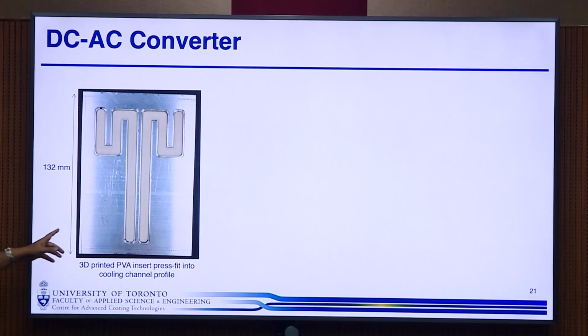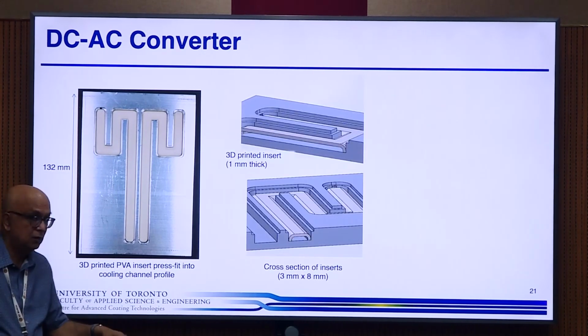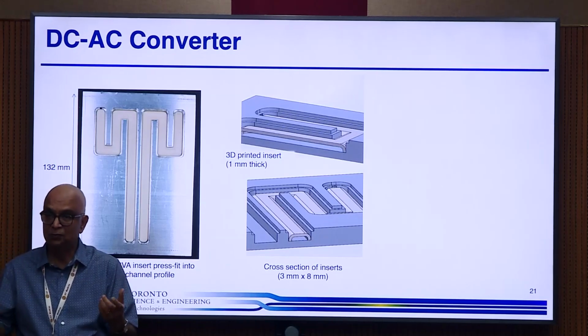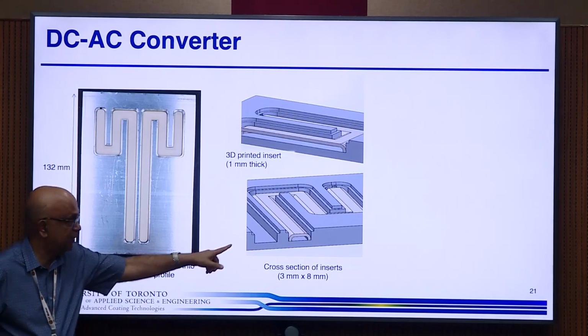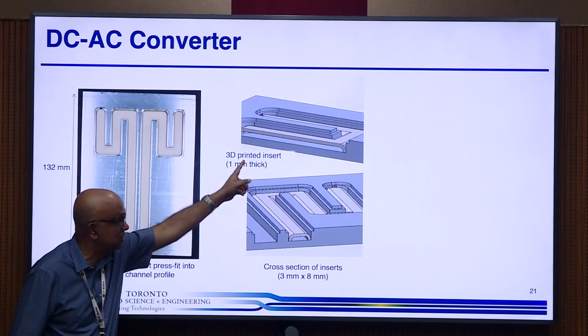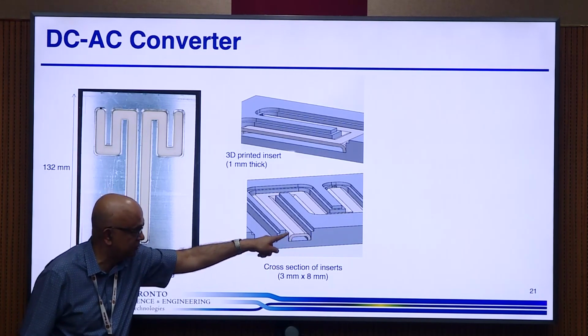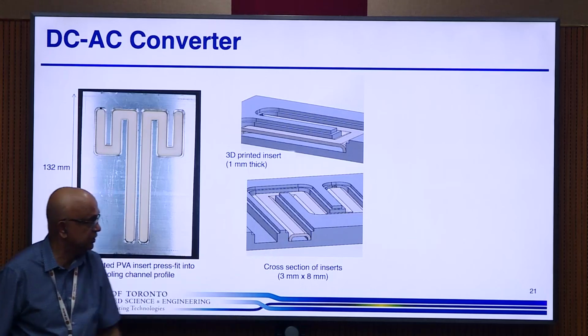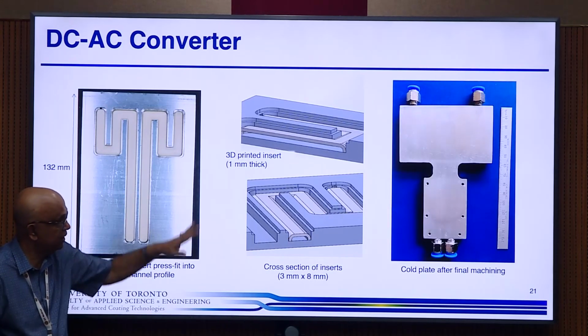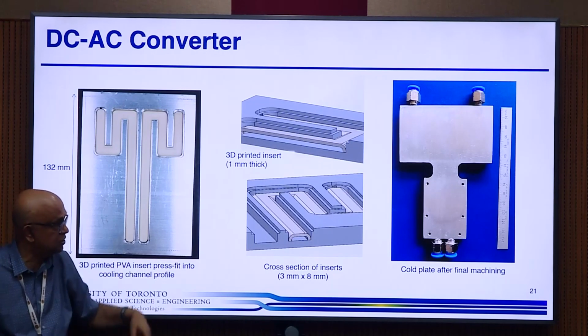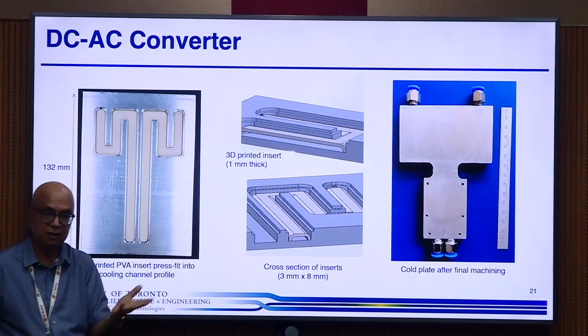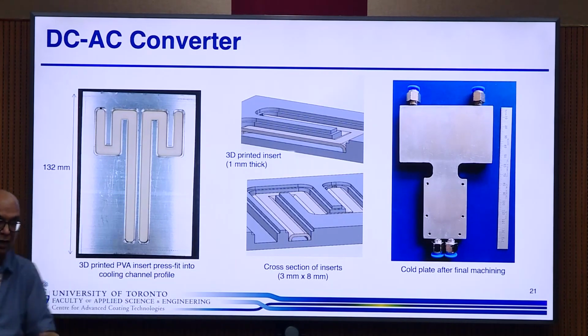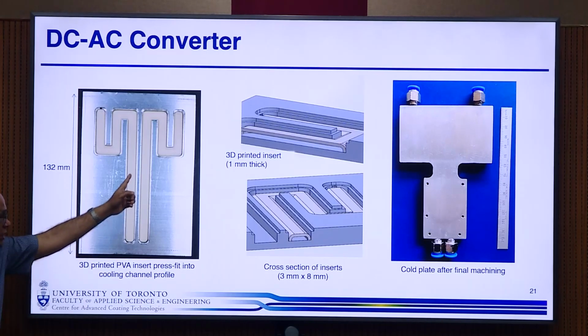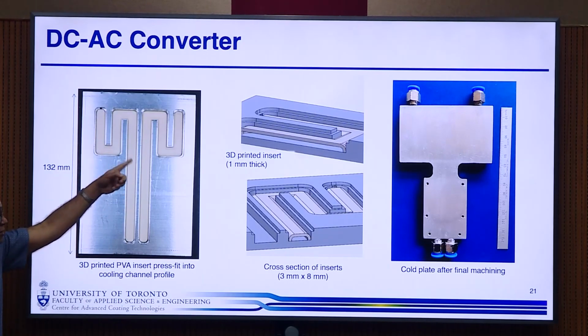So we start off with aluminum plate. Here again, 3D printing out these PVA inserts that we put inside there. And now you don't actually need to be circular. We could make them very thin. So these are about 1 millimeter, about 3 millimeters high, 8 millimeters wide. We spray metal on that, we cut it to size, and this sits right underneath the circuit board. And your heat emitting elements are right over here, the inductors are right at the end.